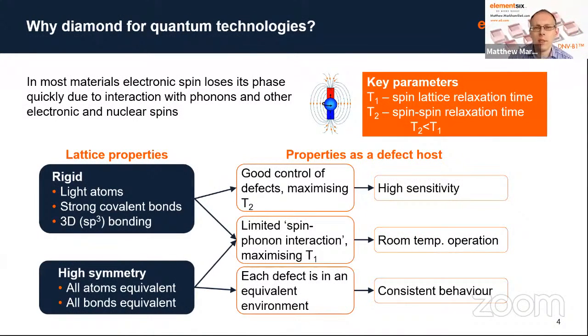So diamond, all of its properties really relate to the lattice properties: the fact that it is a very rigid lattice, with sp3 bonding, so very strong bonds with very light atoms, and a symmetry where all the atoms and all the bonds are equivalent. That leads to all of diamond's interesting properties. But specifically for quantum technologies, it means you have a very high Debye temperature, which essentially means you've got phonons in the material, but they don't generally interact with the electronic spins associated with defects. That leads to the ability to make a material that has high sensitivity for magnetic sensing applications, room temperature operation, and very consistent behavior.